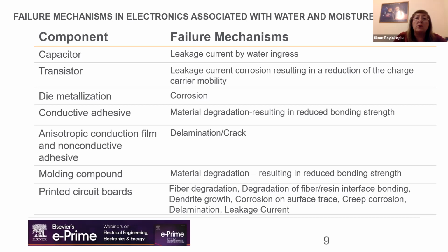Moisture-caused failure mechanisms have been investigated by Sandia Laboratories, and they reported that 20% of electronic failures are caused by water-induced corrosion. These failures, as tabulated here, can be intermittent, short-term failures resulting from water film formation, or long-term failures due to water-induced degradation of the parts. Usually these intermittent short-term failures are unpredictable, given that they depend on transient climatic conditions or unexpected exposure to water. Most of these degradations are irreversible, and they require the replacement of parts.